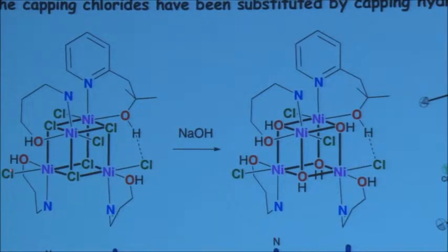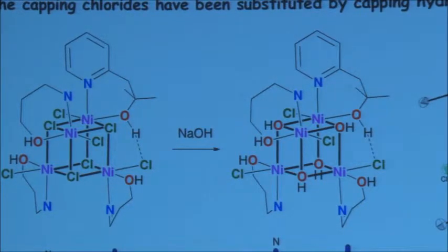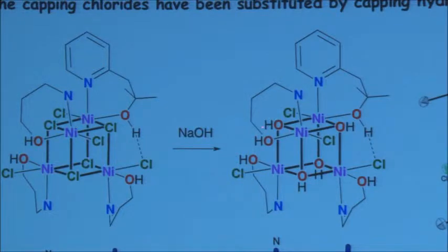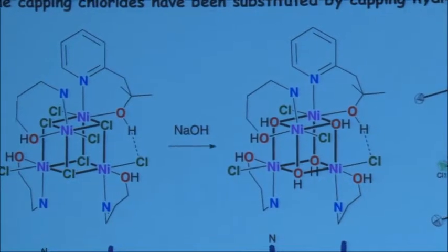So we reacted this cubane with the chloride apices here with sodium hydroxide. Instead of deprotonating the alcohol function, we substituted the chloride with hydroxide groups coming from the base. And that shows you the importance of the hydrogen bonding. This hydrogen here is not very acidic, and it is very much stabilized by this hydrogen bonding interaction. So the sodium hydroxide, a well-established base, does not behave as a base here. It behaves as a nucleophile. It substituted the bridging chloride with hydroxide. So now we have another candidate for catalysis and for molecular magnetism, which again revealed single molecule magnet behavior.